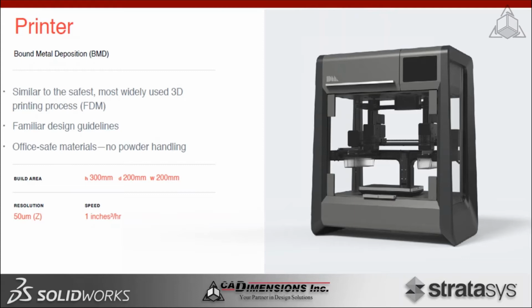As far as build speed, very similar to an FDM system. We're looking at about 1 cubic inch per hour. The overall build area is 12 by 8 by 8. That is the build size of the chamber, but the largest part you can actually build is going to be 10 by 6 by 6. One of the things with the MIM process, if you're not familiar with it, is that the parts are printed oversized by 20%, and when they go through the sintering process, they shrink down to their net shape. So while the build platform will be a little bit larger, your largest part is a little bit smaller, because you have to take into consideration the shrink factor that's going to happen later during the sintering process.